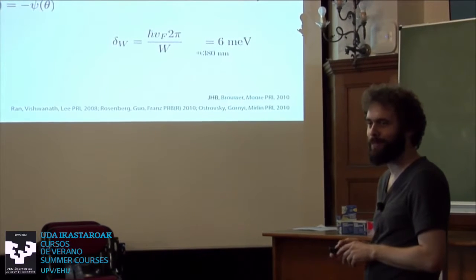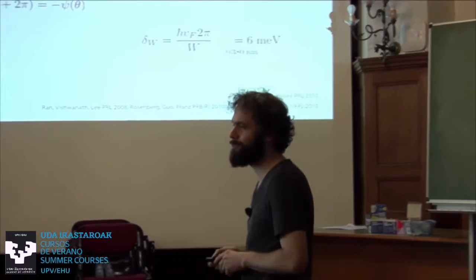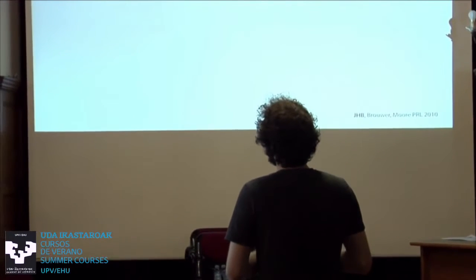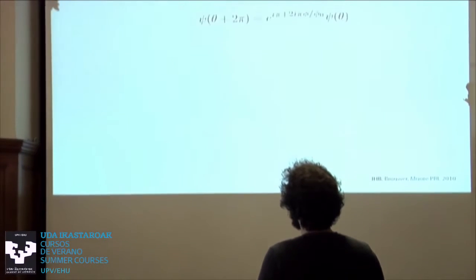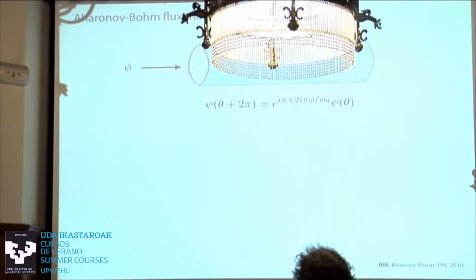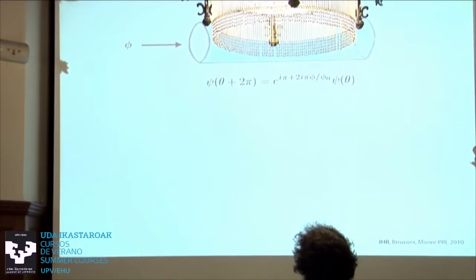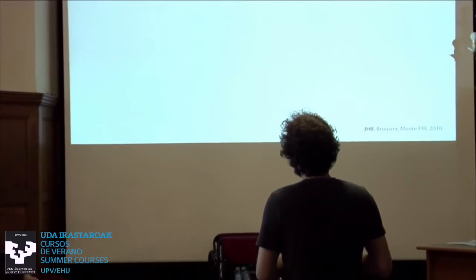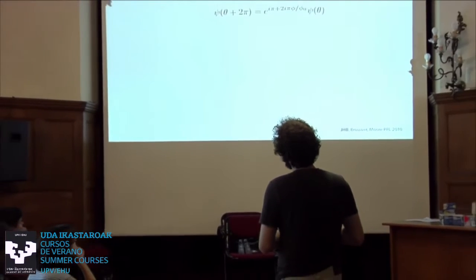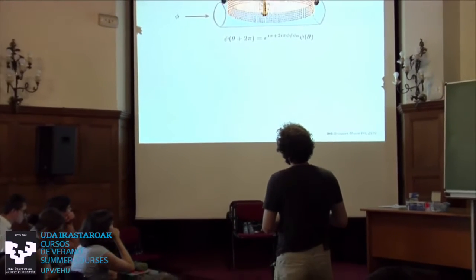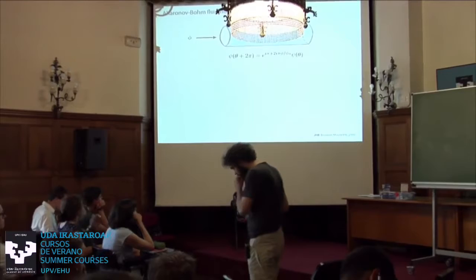I want it to go away. So how do I get rid of the gap? Well, I can simply use an Aharonov-Bohm flux to cancel the pi phase, or the -1 that came from the barrier phase. So I take this wire, and since it's an insulator, I can pass a flux through the core.